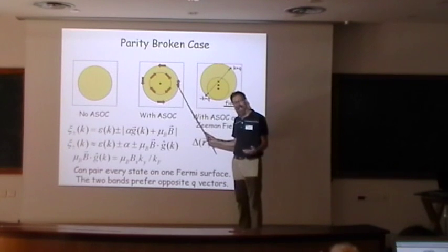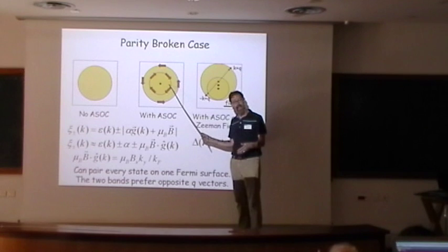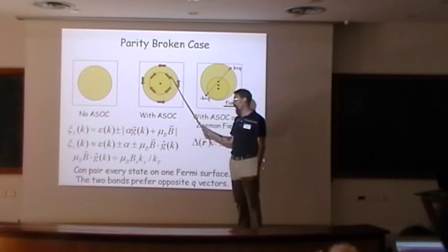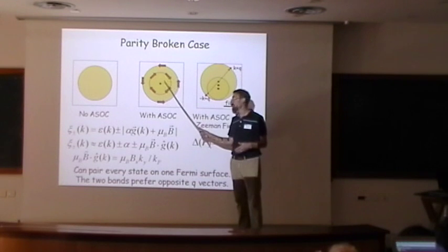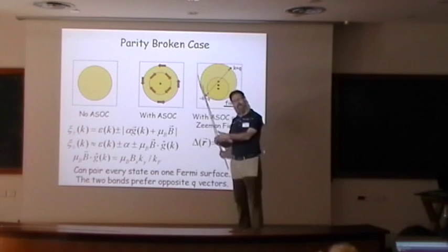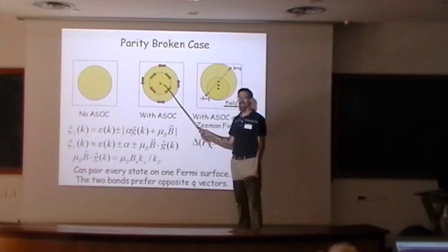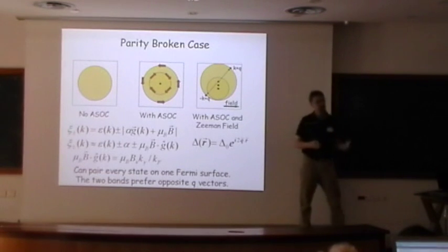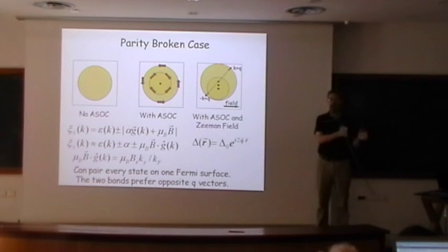And in that case, you know very well that when you add magnetic impurities, the Tc of the s-wave case is strongly suppressed. So it's not obvious that when you have the spin-orbit coupling, even though you can reproduce the usual singlet limit, adding magnetic impurities will have no effect. They're going to have some effect. And it's a complicated issue, as you've seen in two-band superconductors. All the complications that show up there show up here as well.